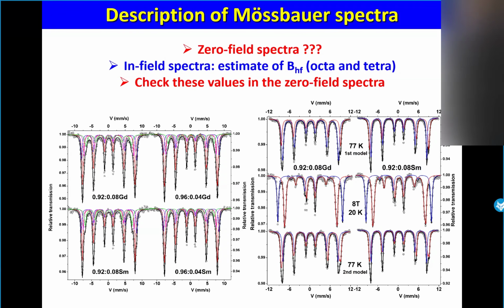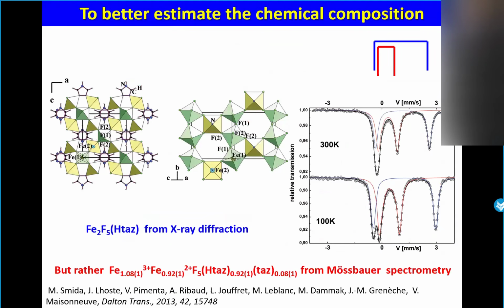And we repeated the fit with this result. Sorry, okay. By considering the result here, we repeated, and it was also well fitted. So it confirms what I mentioned this morning, that it's necessary to perform in-field Mössbauer experiments to get really the proportion of tetra and octa.